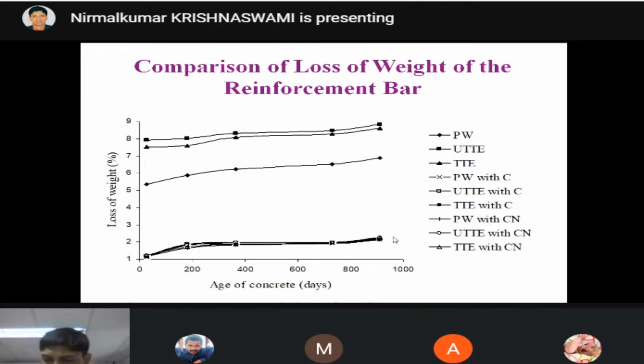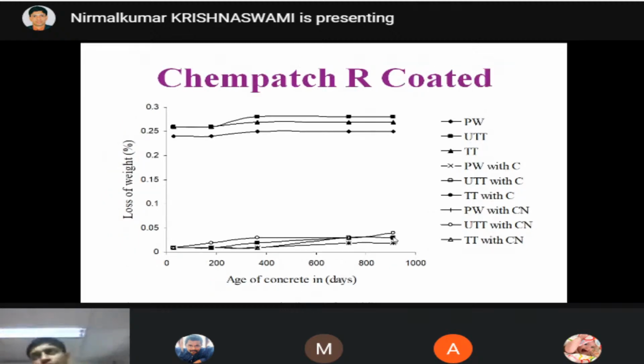Apart from this, I used Chempatch coating. I just coated that steel bar with the Chempatch. When the steel bar is coated with Chempatch, just without any admixtures, this is the result: it is less than 0.3. But with the admixture, the loss of weight is less than 0.05 percentage. Just by coating this Chempatch, total corrosion has been reduced.